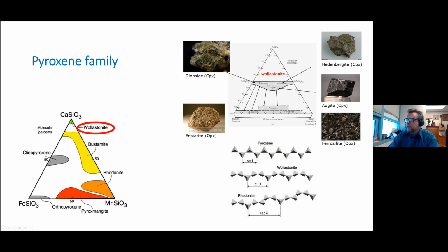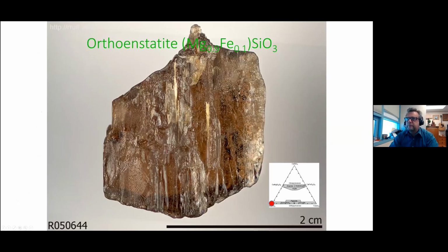This is a compositional phase diagram that shows 3 end members, enstatite, ferrosilite, and wollastonite, which is actually not a pyroxene, but a pyroxenoid. You can see that we have an ability to exchange cations quite significantly and preserve the main structural features of pyroxene. If we put more than 50% calcium, we get to this zone where wollastonite structures are dominant, which means lowering of symmetry and more kinking in the chains, but the general topology of these silicate chains is preserved. So over the last 8 years or so, we've investigated a number of different compositions in this crystallographic and compositional system.